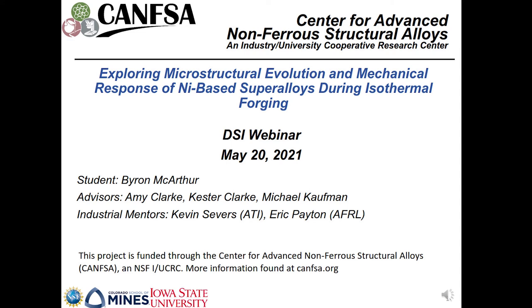I hopefully addressed them in the chat well enough, but I suppose with the processing for the material, usually the higher strain rate extrusion processing creates the incoherent primary gamma prime, which is on the order of a couple microns. There's a range that can be done at both temperature and strain rate. That achieves the distribution that you're starting with of primary gamma prime and secondary gamma prime and the respective sizes of those.